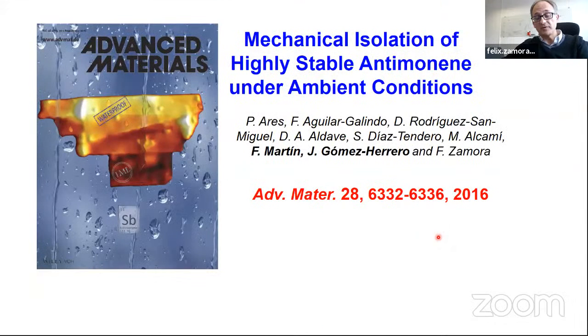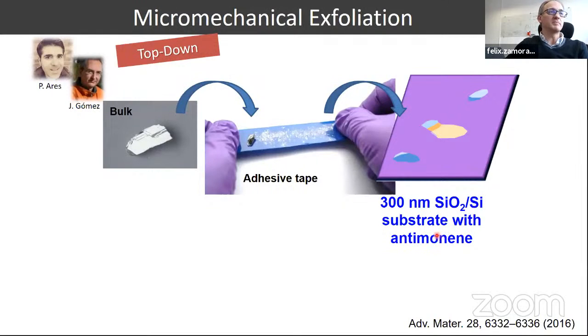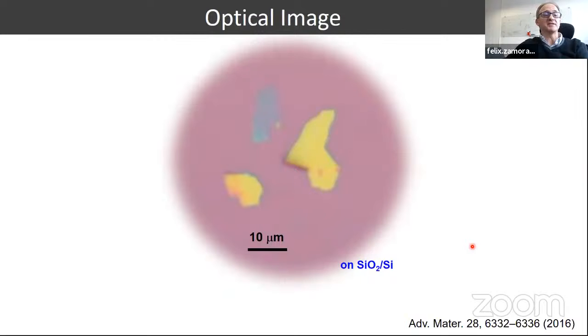Okay, so what we did first was to try to produce the material following the most simple approach, which is what we call micromechanical exfoliation. For that, in collaboration with Pablo Ares and Julio Gomez, we took the bulk crystal of beta antimony, and using an adhesive tape upon several cycles of exfoliation, we had a few layers on the tape, and we transferred them to silicon oxide, and we analyzed what we had on these substrates. Using an optical microscope, this is a typical image. We had these big layers.